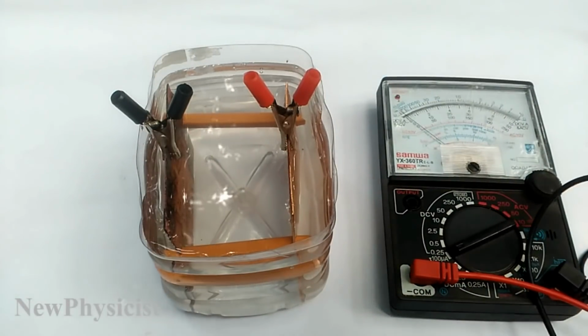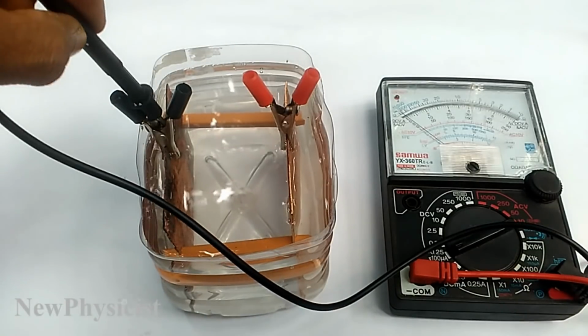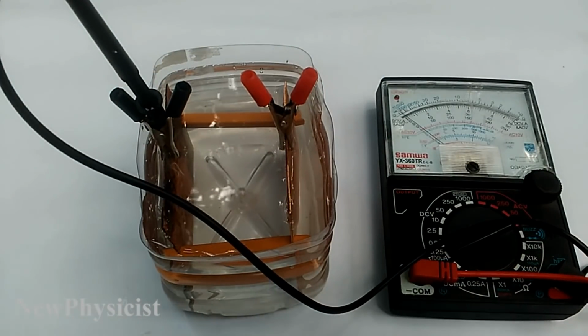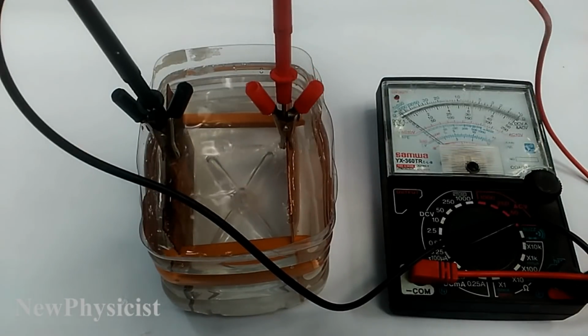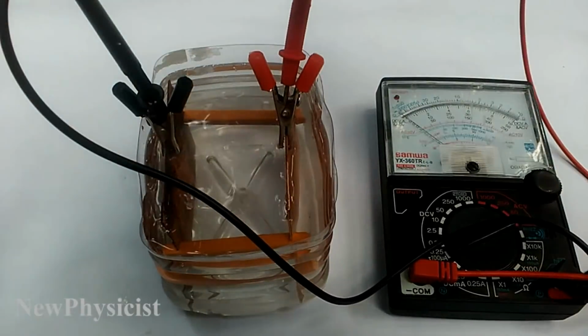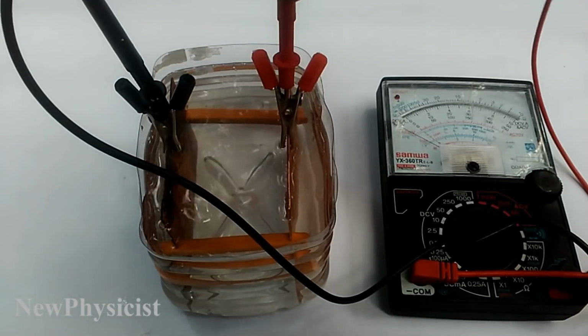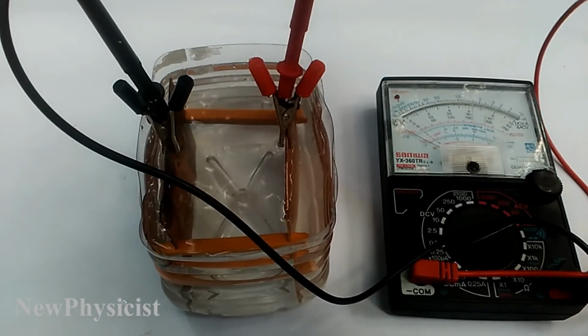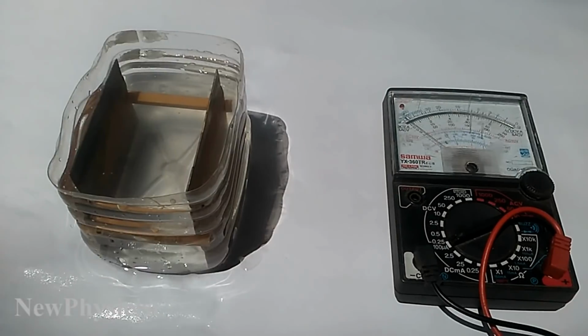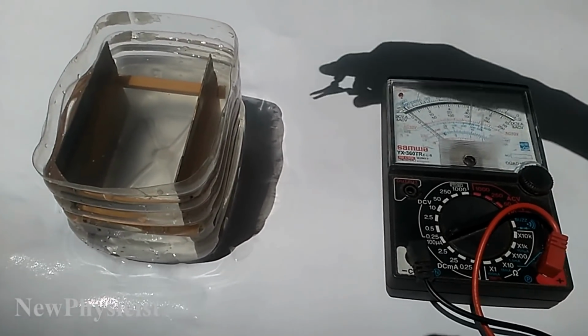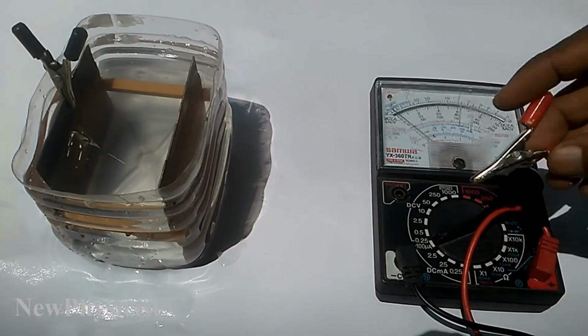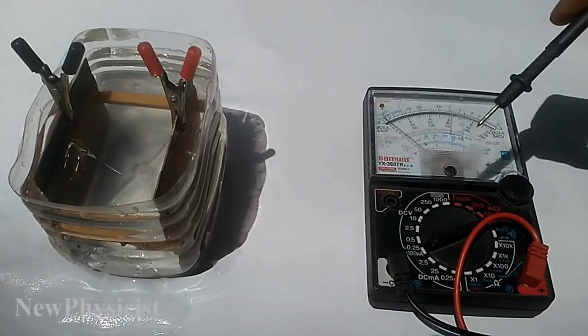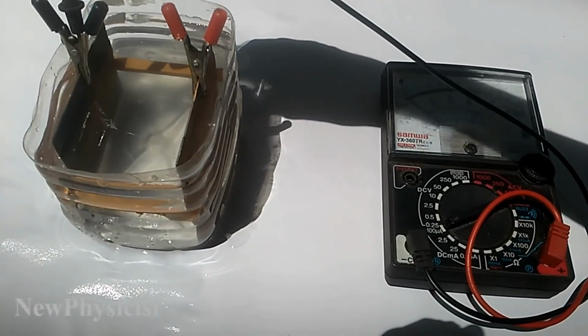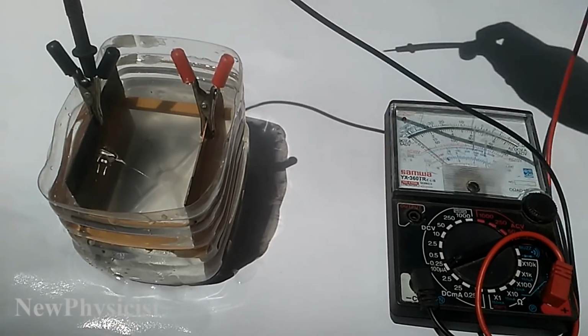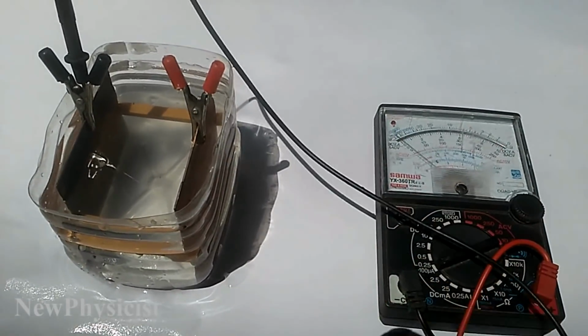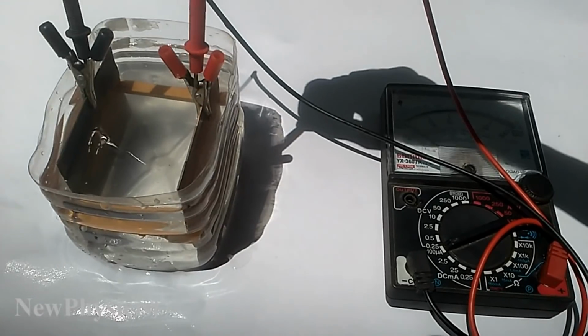Don't forget to set your meter to read microamps. Now you can see a very small amount of current flowing through this multimeter. Turning the cell so that the cuprous oxide layer is facing the most direct sunlight will give you the most current. Unfortunately, this method is not efficient for powering even an LED. It is best suited to show the chemistry involved in making solar panels rather than as a viable solar panel. The contradiction is that it would require acres of land and millions of dollars of copper just to produce enough power to run the hot plate used to cook the copper plate.